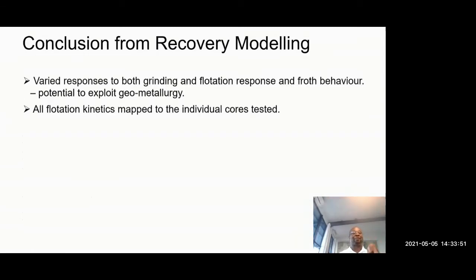So from that particular work that we did for a big project, what I could see then, and we used in the design, was that there were apparently varied responses to grinding and flotation behavior, whichever flotation circuit you put these materials through. The days where the plant treats a lot of material fractions from those places, you're going to have issues. Map all flotation kinetics to the individual cores tested if you can.